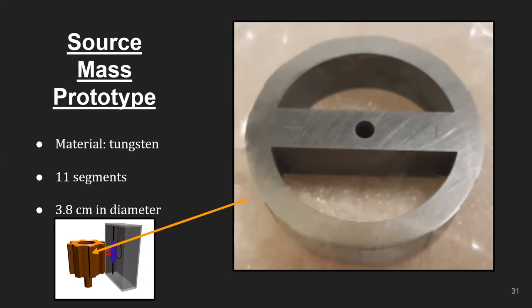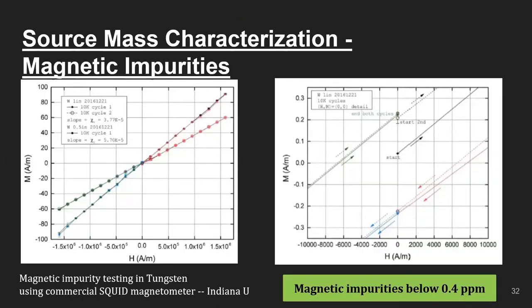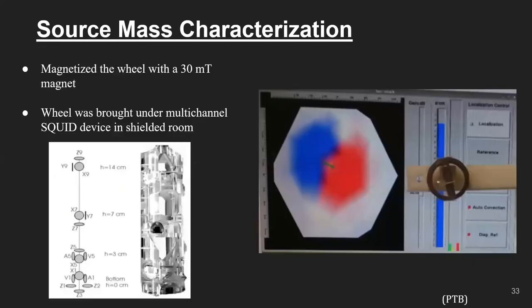We did some initial tests using a SQUID system in Indiana, where we could put some sort of bound on impurities at the level of less than a part per million, which already looks promising. We did some more sophisticated tests following that with our collaborators at the Metrology Institute in Germany, PTB. Here they tried to deliberately magnetize the tungsten wheel to bring out any inclusions or other ferromagnetic domains that might be present.